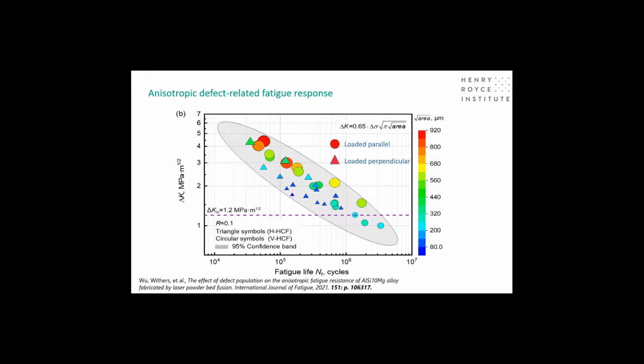If you take that into account, you can again bring all the curves together. If you just plot the stress intensity factor relating to those defects, you can see that largely the differences between the parallel and perpendicular disappear, and they fall more or less onto a single curve. It's not quite true. Those loaded perpendicular now show a slightly lower fatigue resistance than those loaded parallel, and that could be to do with the grain microstructure, which is also anisotropic, and I'm sure we'll see more of that later in this meeting.